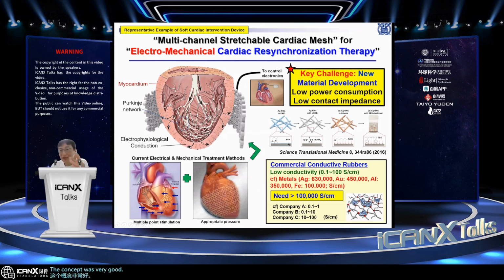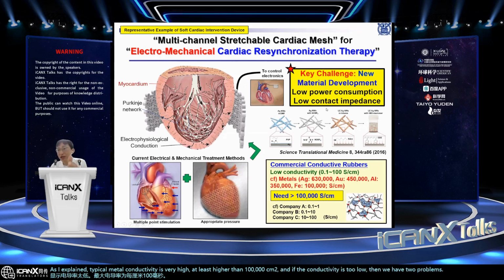The concept was very good, but the problem at the first stage was in the material. We first tried to use commercial conductive rubber, but the commercial conductive rubbers made by Japanese companies or German companies showed conductivity that was too low. The maximum conductivity was 100 siemens per centimeter. As I explained, typical metal conductivity is very high, at least higher than 100,000 siemens per centimeter. And if the conductivity is too low, then we have two problems: large power consumption and high contact impedance.